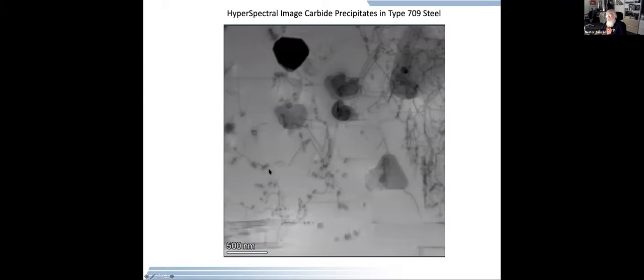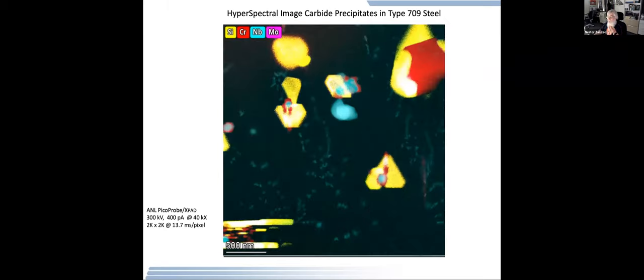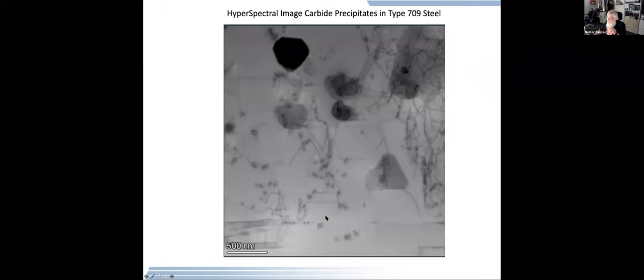You see dislocations. This is precipitates in steel, but very specifically around the cores of these dislocations, you'll see a shadow or an envelope of material being distributed. Question, what is that? Well, we can go in, and again, using hyperspectral imaging, we can map those out. And I'll point out to you that these images were taken where I spent 14 milliseconds per pixel around these precipitates. Not a very long period of time.